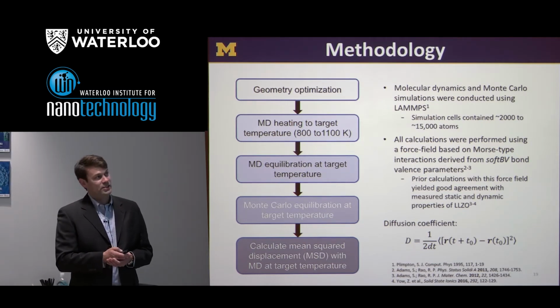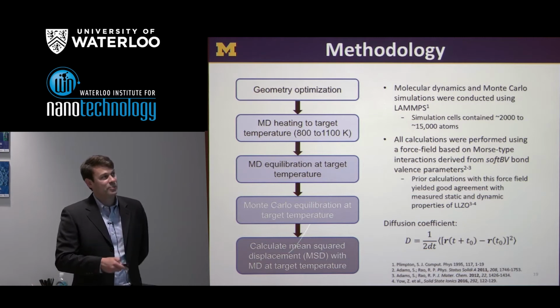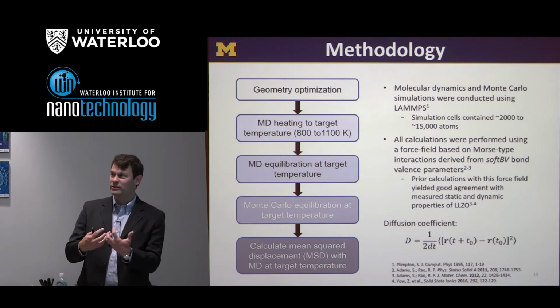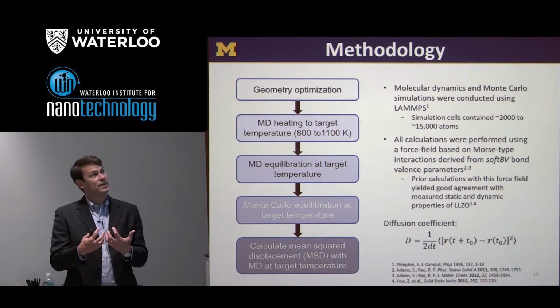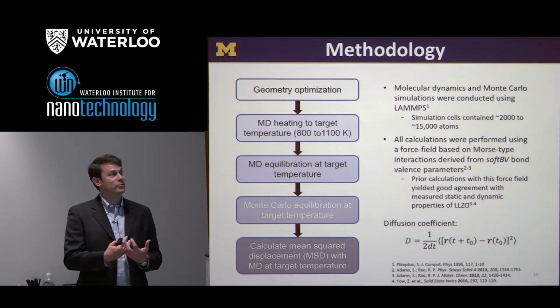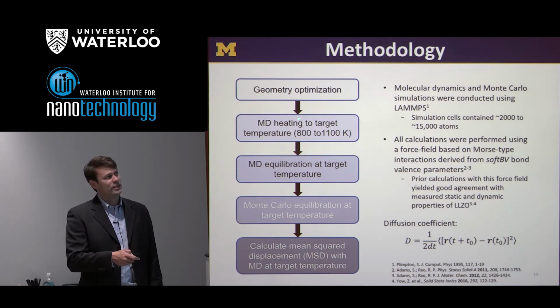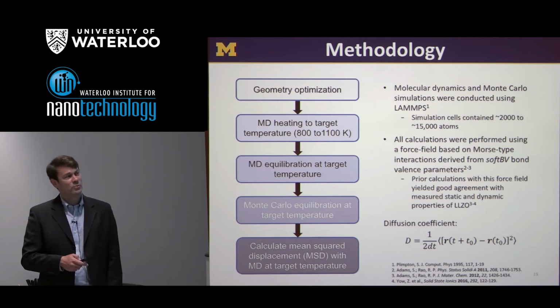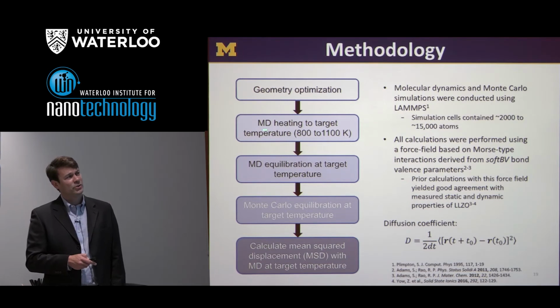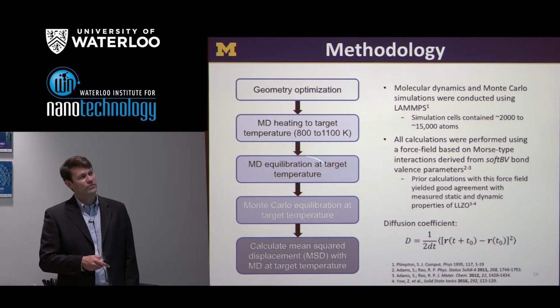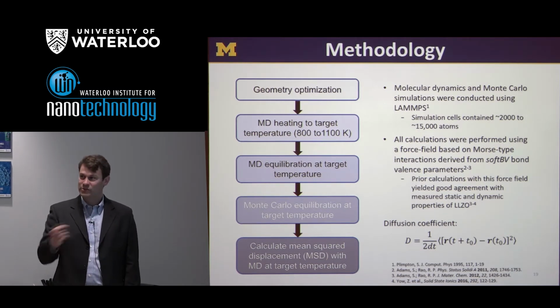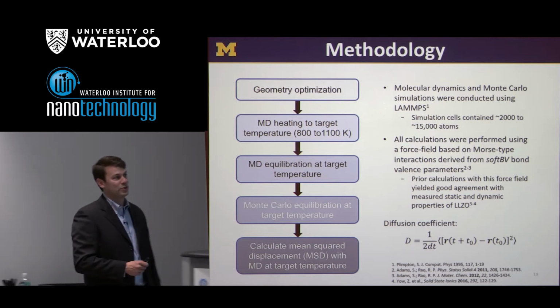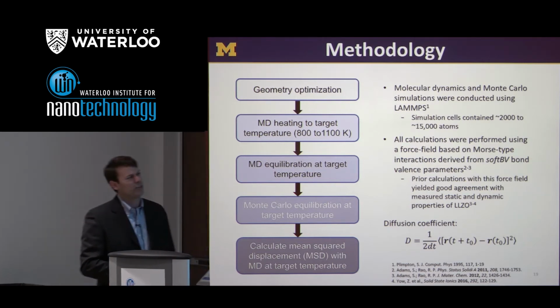And so the way we do that is to follow a series of computational steps. We start off with the as-built structures you saw on the last slide. We relax the forces on those systems first. That's all done at 0 Kelvin, and then we heat to a high temperature. So here we're roughly mimicking some of the processing conditions with molecular dynamics. We equilibrate for another 3 nanoseconds at the target temperature. Then we switch over to Monte Carlo. So here we're exchanging atoms to allow for rapid evaluation of the composition at the grain boundary plane.